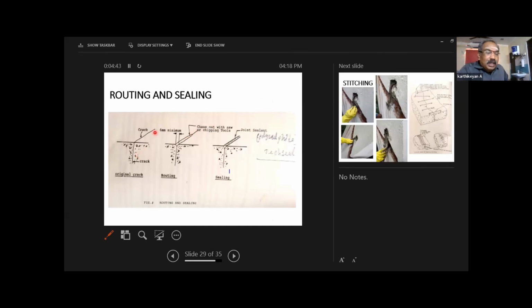Another: in a concrete surface or a brick surface, there is a mild crack you can see, less than 1 mm or 1 mm. How are you going to seal it? It is very difficult to seal such a crack because we don't have any tools to apply on it. So make a groove on the crack. By proper tools, you make a groove so that you can apply a sealant. Mostly polysulfide is used as a sealant. There are other sealants also: silicone sealant, polyurethane sealant. It depends on requirement. If you want the crack only sealed, polysulfide sealant is okay. If you want the crack to be watertight, you have to use polyurethane sealant. So make the crack wider by grooving and then put a sealant.